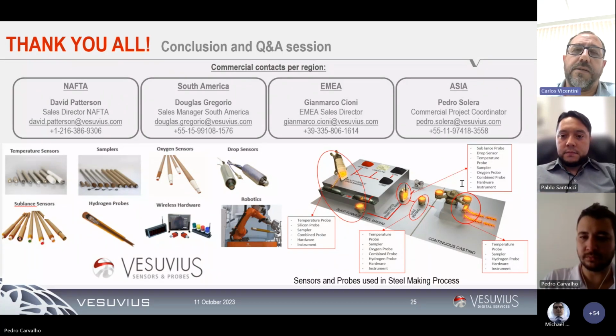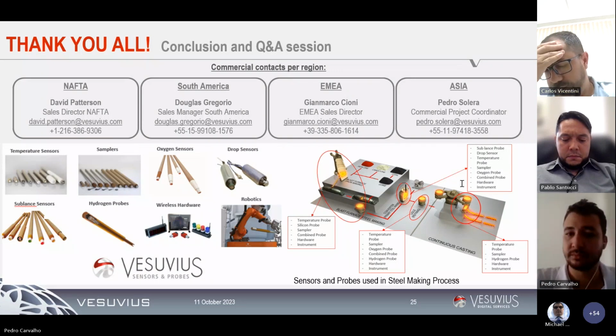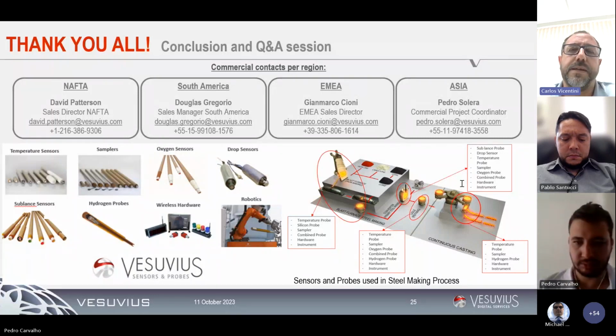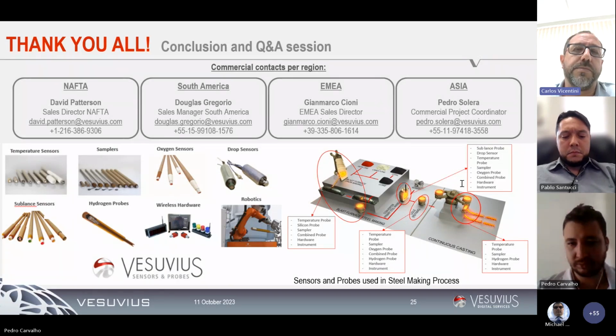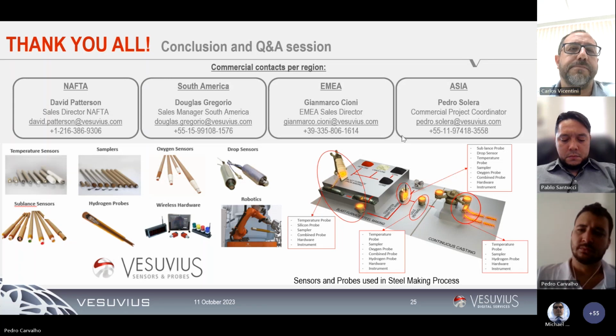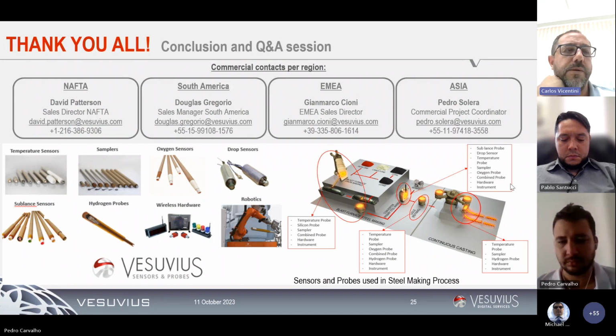Again, it's very important to highlight that when you are talking about within 0.5 to 1 ppm, we recommend engineering follow-up, because we needed to make some adjustments in the equipment specific to this restricted range. Of course, the system is capable of measuring from 0.5 ppm up to 15 ppm, but regularly we recommend you restrict this range as much as possible, or calibrate, check, do liquid tests, etc. As Pablo showed us during this webinar, that is how you get better accuracy from the system.